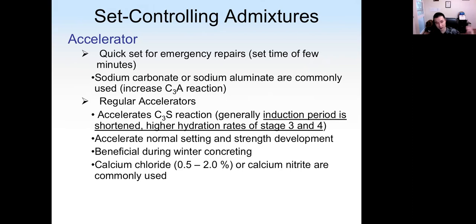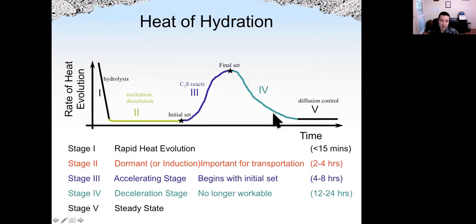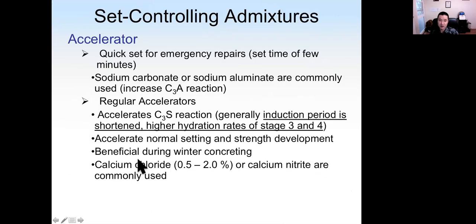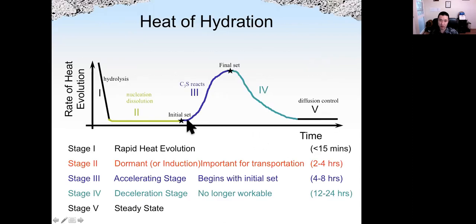The second class is called regular accelerator. So that regular accelerator accelerates the reaction of C3S. So that means the induction period, which is stage 2 here, is shortened by increasing the concentration of the ions. So concentration reaches the threshold concentration in shorter time. So the reaction will be accelerated. It will also increase hydration rate in stage 3 and 4, which is here and here.